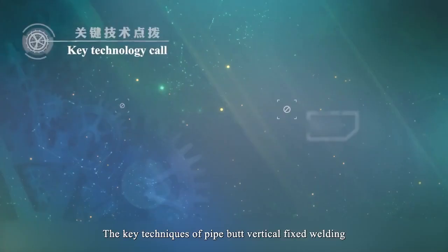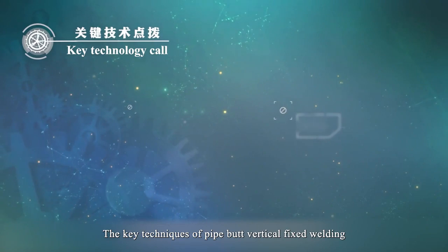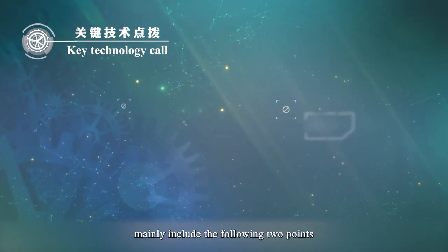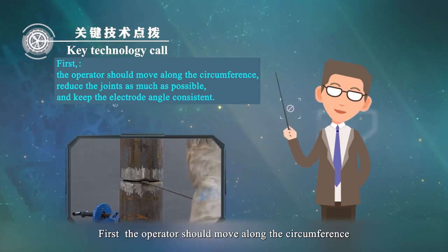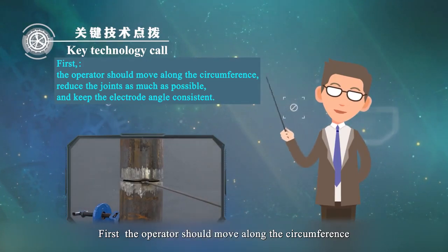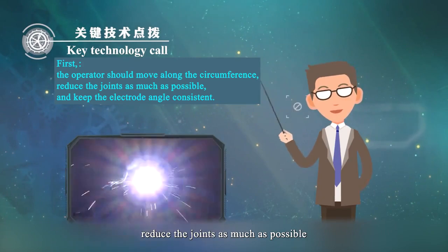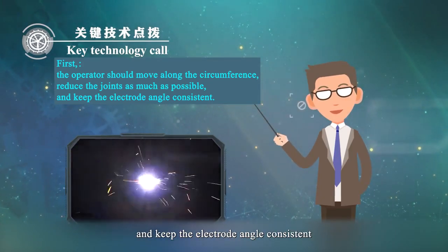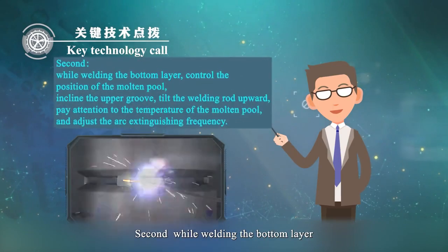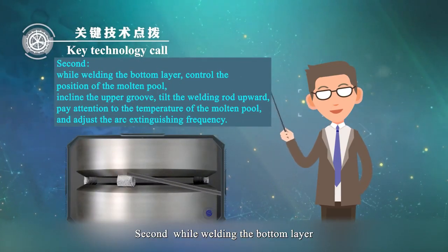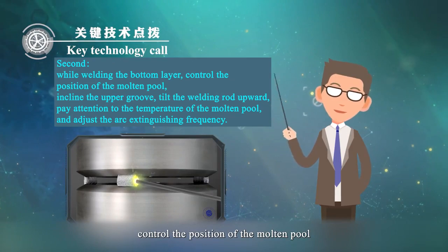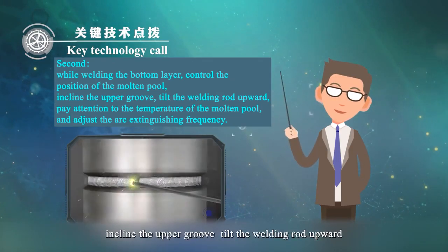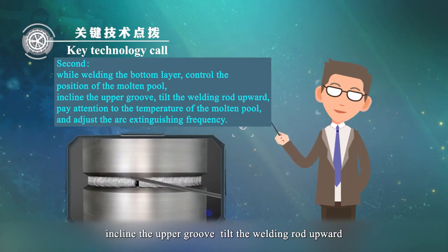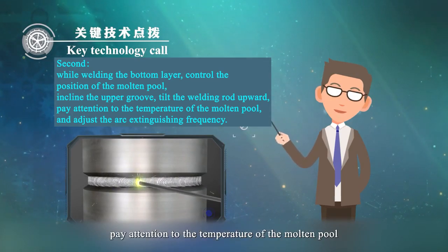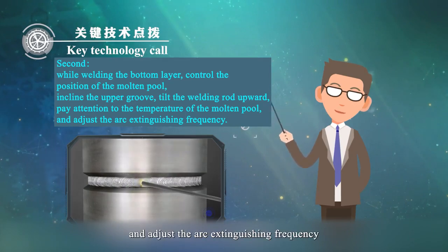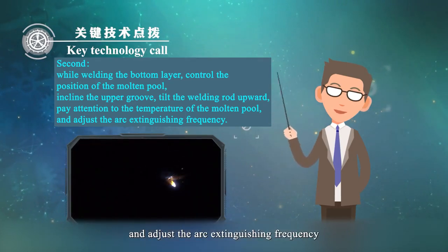The key techniques for pipe butt vertical fixed welding mainly include the following 2 points. First, the operator should move along the circumference, reduce the joints as much as possible, and keep the electrode angle consistent. Second, while welding the bottom layer, control the position of the molten pool and incline the electrode toward the upper groove. Tilt the welding rod upward. Pay attention to the temperature of the molten pool and adjust the arc extinguishing frequency.